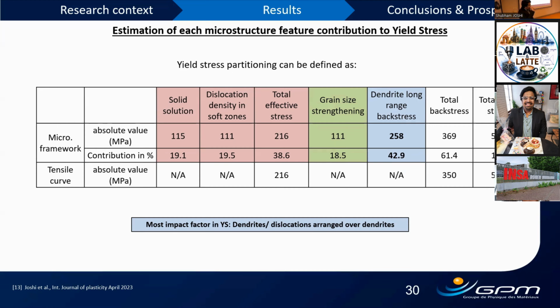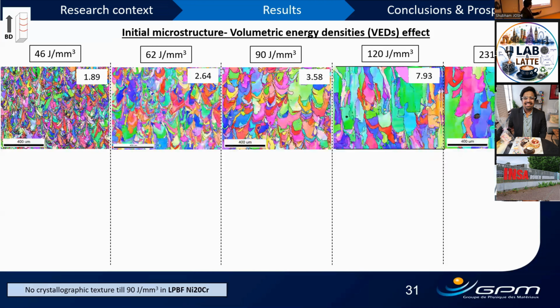But now, if you remember in the literature review, we checked that there could be an influence from process parameters. So what happens when we change the process parameters? Do we still have dendrites as the most influential parameter? Well, the only way to know is to do it. So we tried to take a big range of volumetric energy density as process parameters.